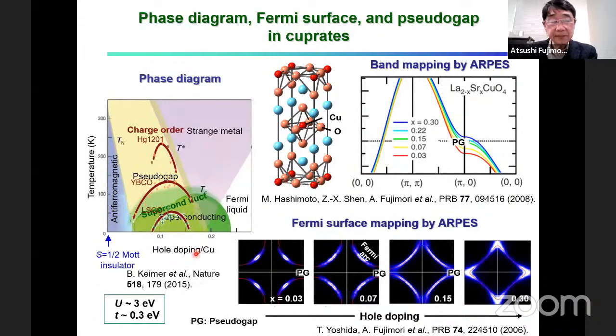Another, more recently, charge ordering has been proposed to be an origin of the pseudogap. This is quite an attractive viewpoint, but the charge order temperature determined experimentally, mostly by resonant inelastic X-ray scattering by many groups, is different between different cuprate systems, LSCO, YBCO, and mercury, and so on. But the pseudogap temperature is quite similar between different materials.